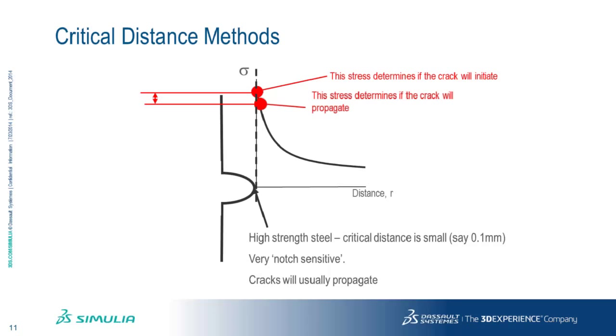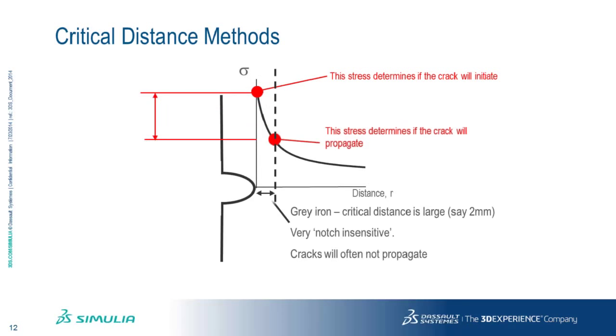If we look at the opposite extreme, which could be a gray cast iron, then the critical distance can be quite large, 2, 3, 4 millimeters. So there may be a big difference now between these two stresses, and so there may be a good chance that if a crack initiates, it will not propagate to failure. So we have been working on implementing the theory of critical distances now for several years, 8 years, I think. The 6.5 release is our best release yet of the theory of critical distances.